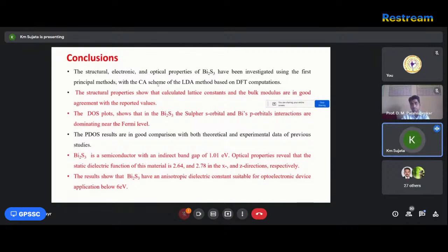Conclusion: the structural, electronic, and optical properties of bismuth sulfide have been investigated using the first principle method with the CA scheme of the LDA method based on DFT computation. The structural properties show the calculated lattice constant and the bulk modulus are in good agreement with the reported values. The DOS plot shows that in bismuth sulfide, the sulfur s orbital and bismuth p orbital interaction are dominant near the Fermi level. The PDOS results are in good agreement with both theoretical and experimental data of previous studies.